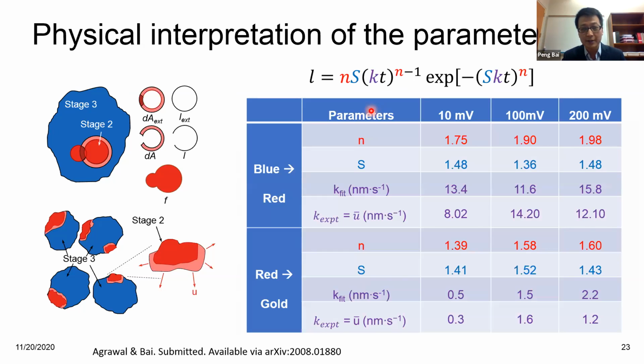Not the derivation, but the parameters. So here we really have just 3 parameters. The right one, the n, is a dimension exponent. For this case, we are studying a 2D process, so it should really be 2. But you can see here for different experiments, we really got something close to 2, especially with 200 millivolt steps. It's very close to 2. But we also consider there is inaccuracy when we characterize the color areas, and there is variance in the thickness of the particles. So this is acceptable.